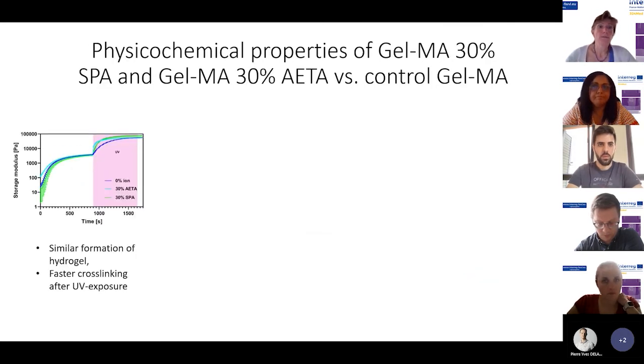So then what did we do? First of all, we tested the physical chemical properties of these types of gels. We took pure GelMA as a control condition, because this is a hydrogel that is used a lot in tissue engineering applications, and it has been shown to have excellent properties as a hydrogel. And then we also used GelMA containing 30% of the SPA ion or 30% of the AETA ion.